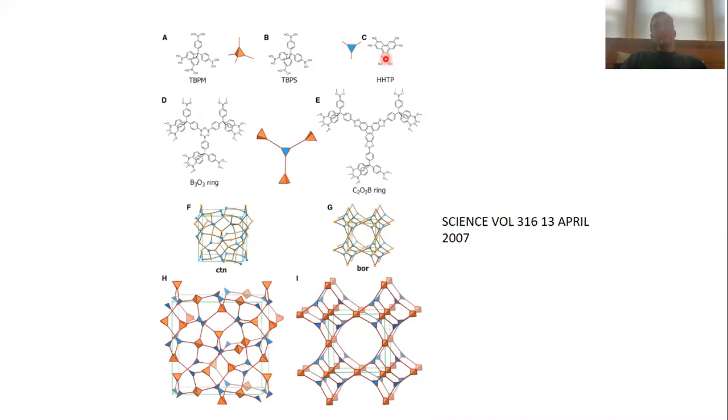the formation of a three-dimensional covalent organic framework, which has a 3-4 connectivity. Okay, so you interconnect these tetrahedral building blocks with trigonal planar building blocks. So when you use hexahydroxytriphenylene as a unit, then you will have this hexahydroxytriphenylene as a tritopic linker.